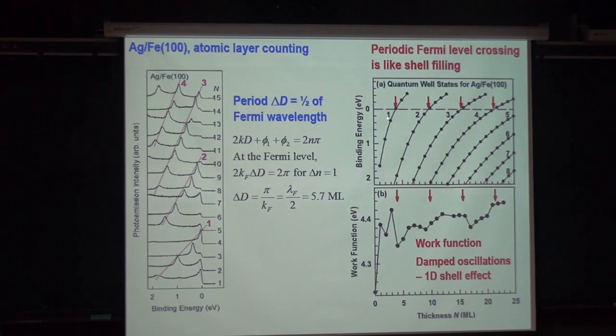So you can see they move up in energy and go to the Fermi level and the Fermi level cuts them off. And then every now and then one of them will cut through the Fermi level and disappear. And these are theoretical curves, they actually fall right on the data.